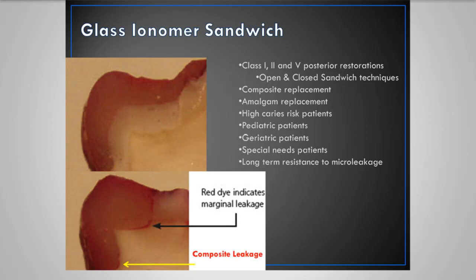You'll notice the composite has entirely absorbed all the red dye, the same as the one here. Glass ionomer has not. So if you do have penetration over time and or microleakage from your traditional composites, the nice thing is the glass ionomer acts as a reservoir, kind of an insurance plan sitting under here, that when it does fail, you really only have to take off the superficial composite and maybe a little bit of the glass ionomer if you want, such that you still have a fresh layer of glass ionomer underneath in which to adhere to, and it's still protecting the tooth.